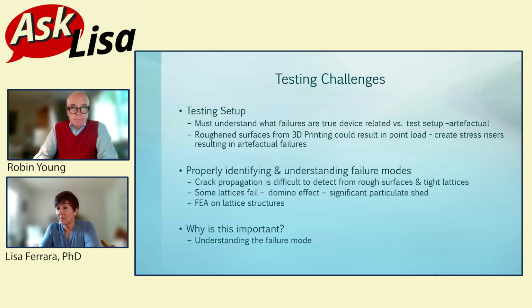And we put these per the standard in Delrin inserts. You test them statically, but then you'd use Delrin. Well, Delrin's still pretty hard. It's harder than bone. And so if your inserts to hold them in the test machine, those are the gripping fixtures, are not fitted properly, or you've got what we call the point loading from the surface texture, you can get an early catastrophic dynamic failure. And you really need to understand that. It may not be related to the device, and that's not fair.